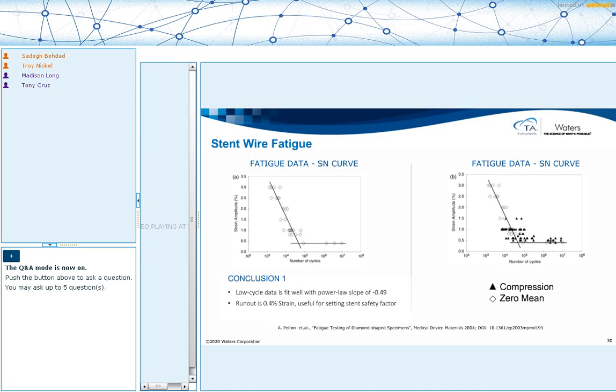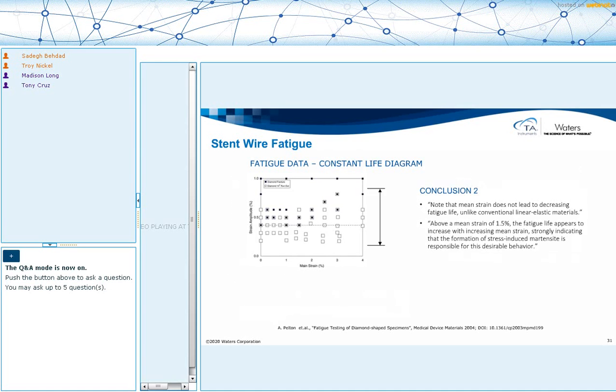Then the second conclusion was another way of looking at the same data. So here, what is shown is called a constant life diagram. So you are pulling and pushing these samples to a known number of cycles. Here it is 10 million cycles. And the hollow dots show the samples that survived 10 million cycles. The solid squares show you the ones that broke.